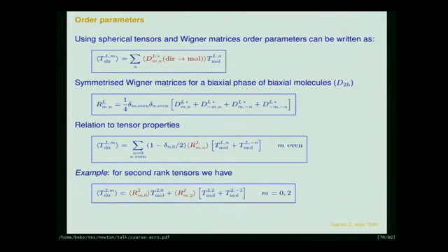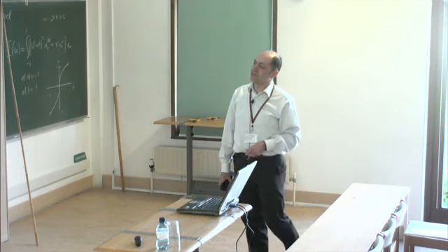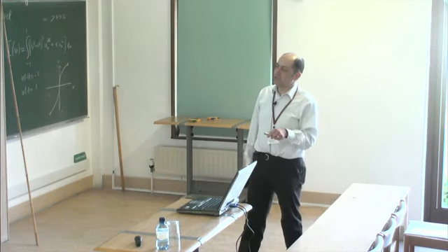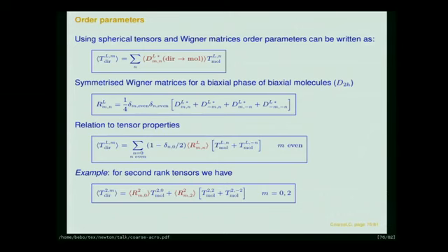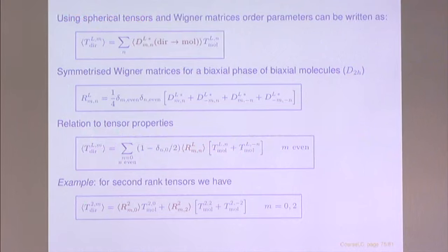So we have 3 ordering matrices, and if we consider in a formal way the transformation from molecular property to director frame, one has to use some rotation matrices, and eventually averaging and symmetrizing with respect to a certain symmetry of the molecules and the system, one can end up with explicit relationships linking the properties measured with respect to the director to the property one knows from the molecule, and the coefficients that perform this transformation are the order parameters.